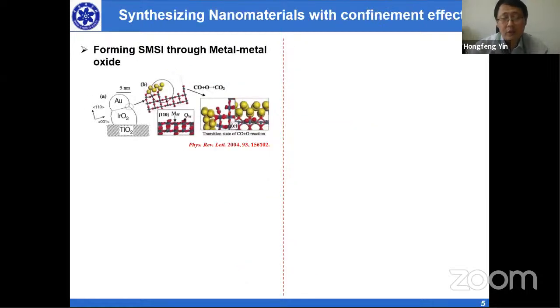To solve the problem, we have proposed to do this. We prefer to form the strong metal support interaction through metal oxide. For example, if you put the gold on iridium oxide, the gold and iridium oxide have very strong metal oxide interaction. Then the gold itself will be bound to the iridium oxide, and when there's a high temperature, the gold will not aggregate because it's being controlled by the iridium oxide. So by forming the strong metal support interaction, it can be a way.